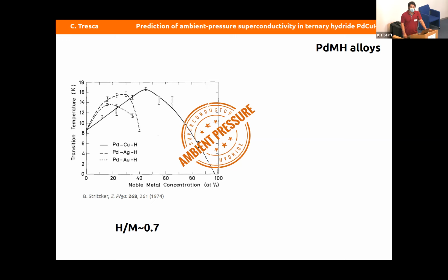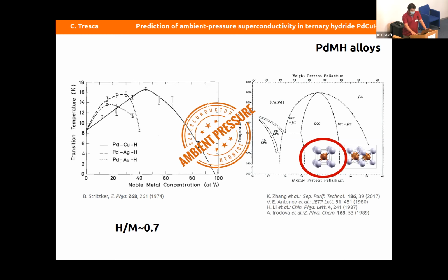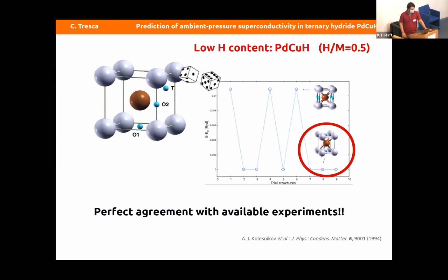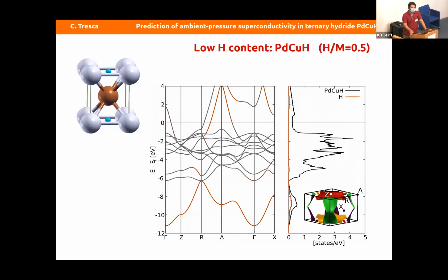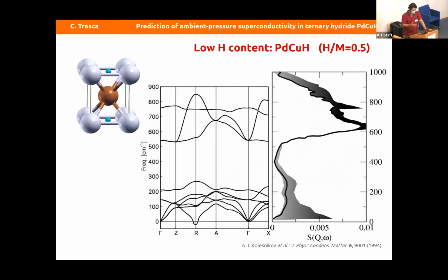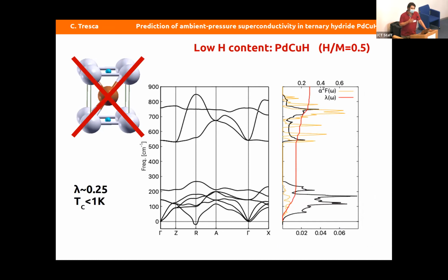So we perform theoretical density functional theory calculations on the palladium copper hydrides in low and high hydrogen content. Starting from the palladium copper alloy, we start with the low hydrogen content. We were able to predict all the structural parameters that are in the literature. Hydrogen acts like an electron donor, and we also studied the dynamical properties, which are characterized by the presence of a gap between low energy metal modes and high energy hydrogen modes, as in analogous experiments. We estimate the electron phonon coupling and the critical temperature, which is below 1 K. So this is not the phase we are searching for.